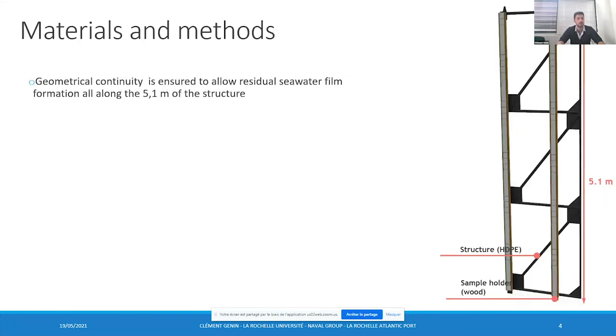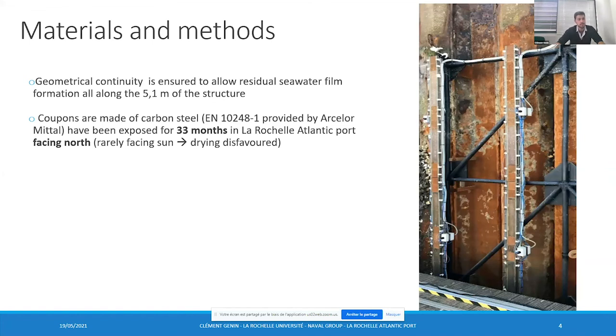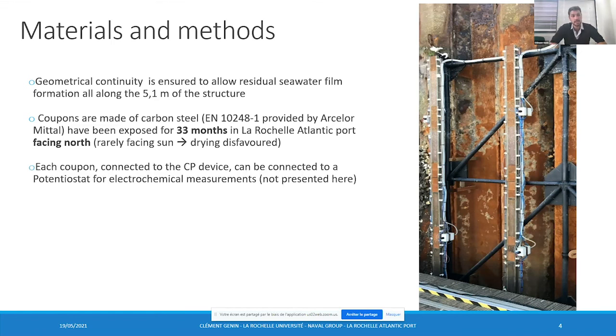This study focuses on a structure like this one, where the geometrical continuity between the samples is ensured to allow the residual film formation along the whole structure. This is the real structure exposed in the La Rochelle Atlantic port, facing north. This is important information because the drying conditions are disfavored, as the structure rarely faces the sun. Each component of this structure is individually connected to the anode and can be connected to a potentiostat to perform some electrochemical measurements, which are not presented here.